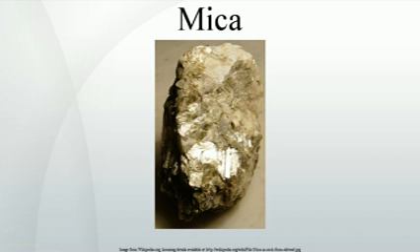Muscovite, the principal mica used by the electrical industry, is used in capacitors that are ideal for high frequency and radio frequency. Phlogopite mica remains stable at higher temperatures, to 900 °C, and is used in applications in which a combination of high heat stability and electrical properties is required. Muscovite and phlogopite are used in sheet and ground forms.